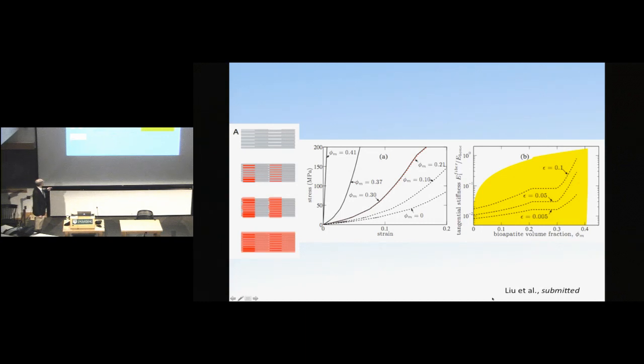So this phi is a volume fraction of mineral. Then our phi sub m at 0.21 is the volume fraction of mineral corresponding to having all of these gap channels filled. And then beyond that, as mineral starts to grow on the outside of these fibrils, you see very little stiffening. And that makes sense intuitively because at this point, a collagen fibril